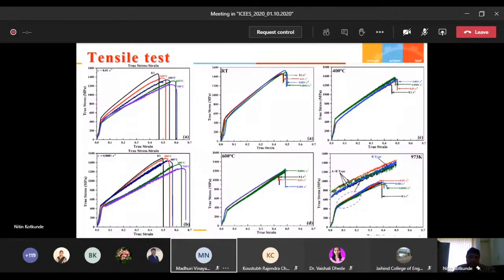If you see here, you can find some serrations. That serration is usually called dynamic strain aging. It is called dynamic strain aging, which is a very adverse effect on the material, found at some particular strain rate and temperature, in which the material will start to behave like a combination of ductile and brittle fracture.